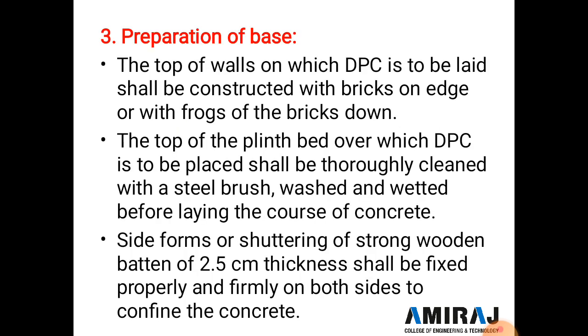Now the third specification is the preparation of the base. So here the top of the wall on which DPC is to be laid shall be constructed with bricks on edge, or with the frog of bricks down. The top of the plinth bed over which DPC is to be placed shall be thoroughly cleaned with a steel brush, or washed with water before laying the course of concrete.